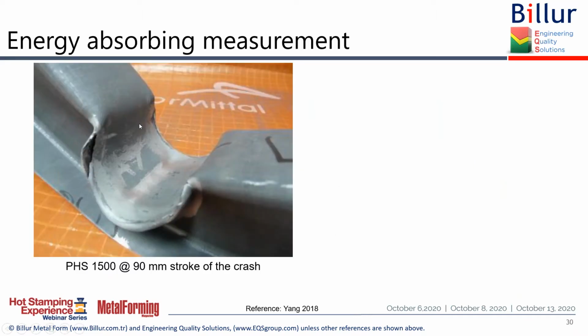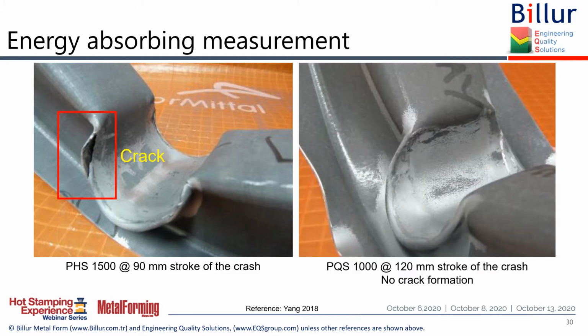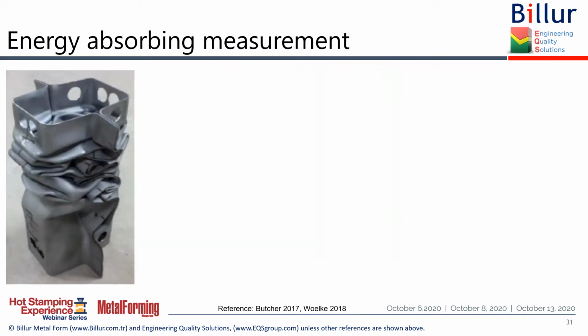Here you see a 3-point bend of a hot stamped part, and at 90 millimeter stroke of the crash, you would see cracks forming. So its structural integrity is already broken, and it cannot withstand the load anymore. And here you see PQS 1000 at 120 millimeter stroke of the crash, and there's no crack formation. And once again, their total elongations are pretty close.